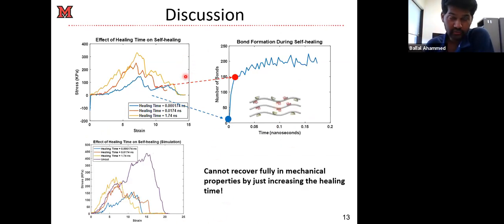So when we looked into the behavior, like bond formations between the crosslinkers, we found that the bond formation between the different crosslinkers during the self-healing time increases very rapidly at the beginning, and as time goes on, it flattens out, because those pairs find each other. In some cases, they are not capable of finding each other. Originally the rate is very high, because there are a lot of crosslinkers available to find each other and crosslink. So the other pairs may remain unable to find their pair and remain uncrosslinked. So the bond formation increases exponentially, and then it gets flattened out.